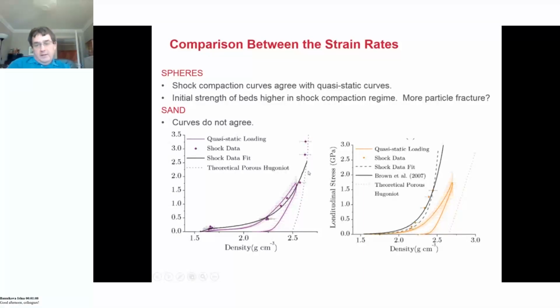But with the sand, here is the fully dense response. Here is the Brown et al. data from 2007, and here we have our data as well. And what we find is, well, here's our shock data, here's our quasi-static data, and here is the theoretical porous Hugoniot curve. So glass spheres, because of their nice shape, because of their consistent packing, etc., show really consistent behavior. The sand really doesn't fit into these simple models at all. You hit the sand hard, you will get a response which is stronger, shall I say, than what you see if you deform it gently and slowly.